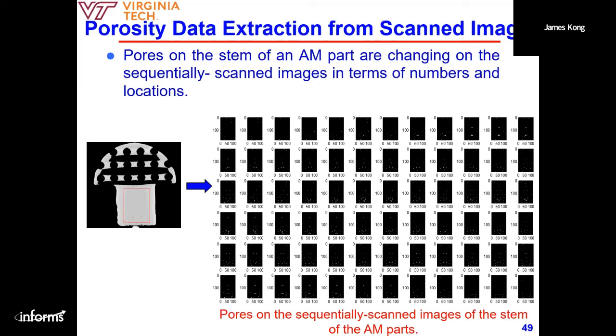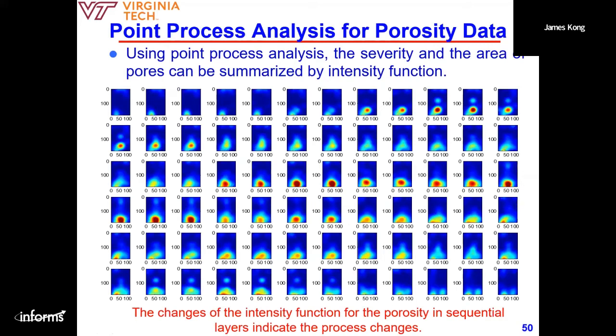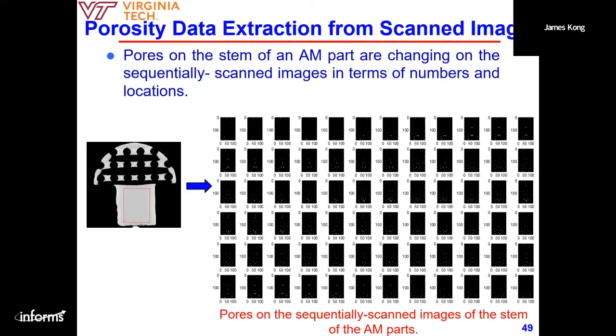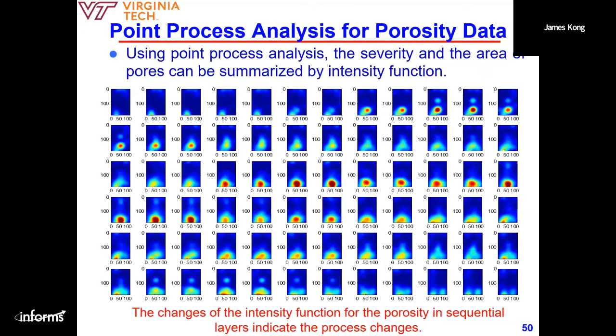And we developed methods to capture the density of each layer of those porosities. We use the log normal Cox process modeling, and also combine the size of the porosity. So instead of this raw data, in the raw data, we can see some sort of patterns. At the beginning, the porosity is not that much, and eventually increasing and increasing, and also decreasing, right? It's layer by layer. But now we are using the statistical modeling. We can precisely capture the spatial and the temporal correlation. Because layer to layer, they have some sort of temporal correlation. Within each layer, we do see this strong spatial correlation, right?